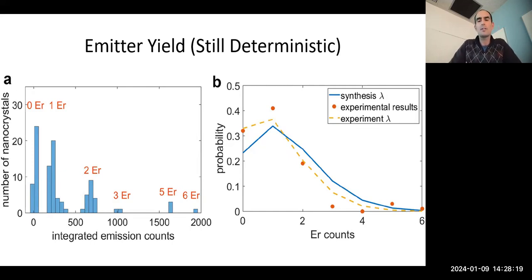We did this with 3 different concentrations grown, very dilute and then slightly higher concentrations. We noticed systematically that the amount of emitters was slightly less than expected from synthesis. So based on stoichiometry, you design your chemistry to give you, let's say, 1 or 2 emitters per nanoparticle, but actually you end up seeing only 1 emitter per nanoparticle, or slightly less than 1.